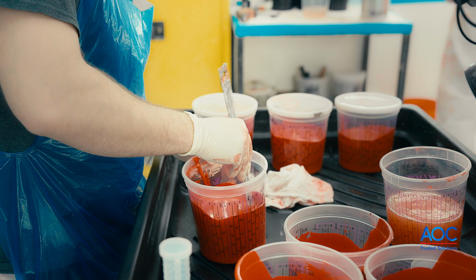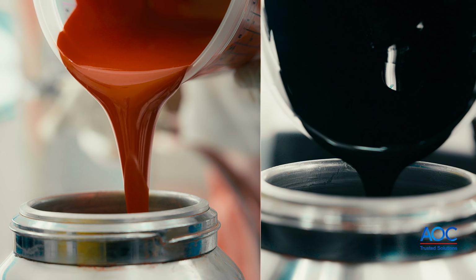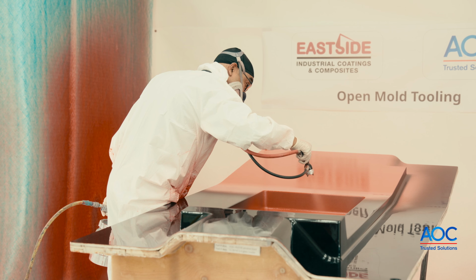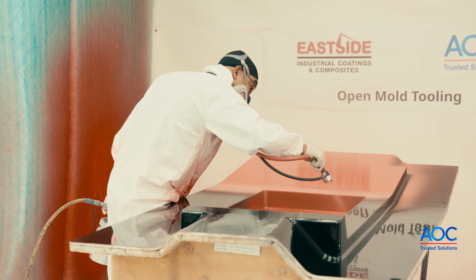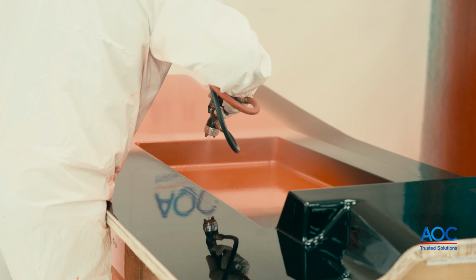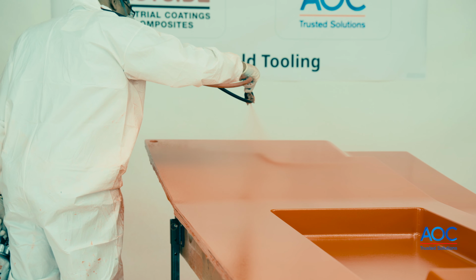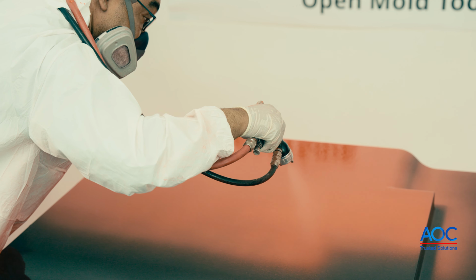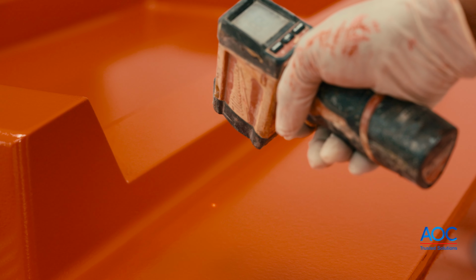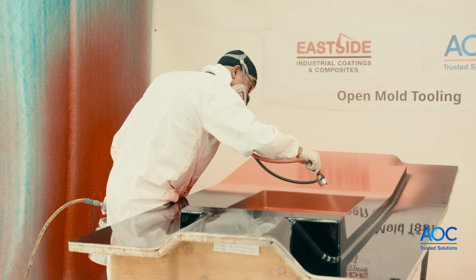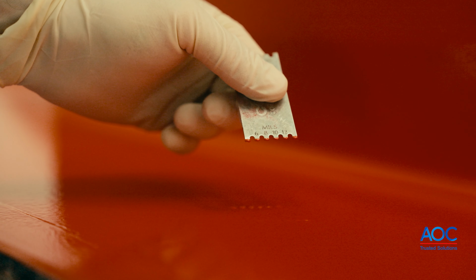Start by preparing the gel coat. Mix it with the catalyst according to the product specifications. Apply the first layer of gel coat. Spray with long, even, vertical and horizontal passes with 50% overlapping strokes, building the thickness with multiple passes. The total thickness of the wet gel coat should be 20 mils, which can be confirmed with a mil gauge.